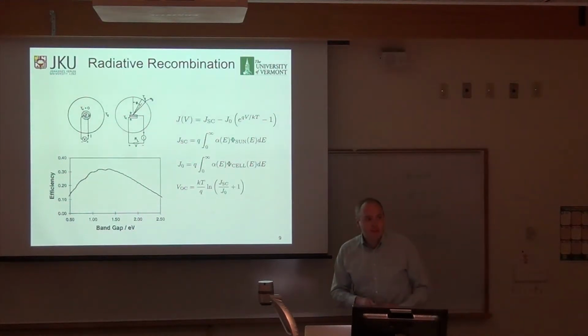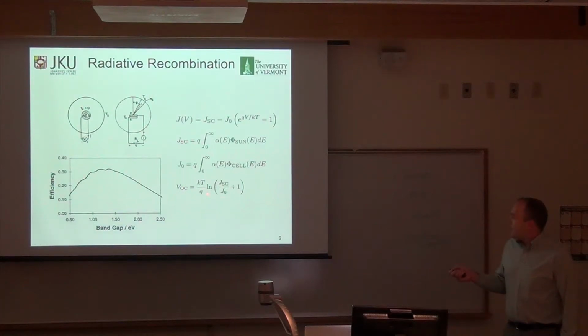That depends on what temperature the cell operates at. But this loss, this J0 over JSC loss, accounts for a loss in the open circuit voltage of the solar cell. So you can never have a VOC of your solar cell equal to the band gap. It's always less because of this.